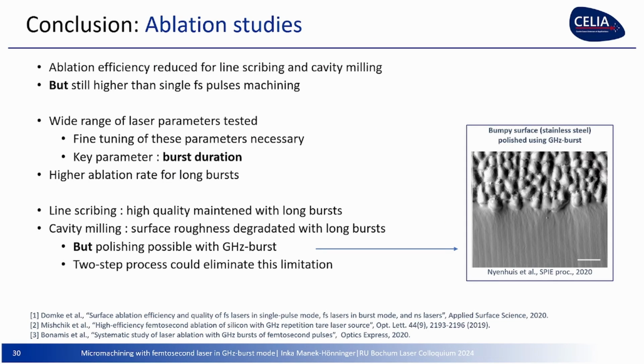To conclude on the ablation, we saw it can be reduced for line and for cavity milling, but it can still be higher than for single pulses. We have a wide range of parameters. The key parameter is the burst duration. And for line scribing, even the good quality comes with the high efficiency. For cavity milling, it's not the case. However, a group at RU Bochum showed in this very nice paper that you can polish afterwards, and a two-step process with high efficiency ablating and then successive polishing might be a very good solution for cavity milling.